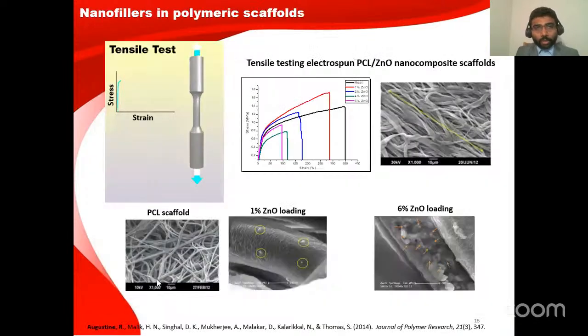We used nanofillers. Nanofillers are nanomaterials that are incorporated in the polymers to improve the properties, especially the tensile properties. We found that when we incorporated zinc oxide nanoparticles in the electrospun scaffolds, there was an improvement in mechanical properties at optimal concentration. The importance of such research is that we need to find the specific concentration of the nanomaterials used in the scaffold. For example, here 1% of nanomaterial seems optimal, with enough mechanical property, while when we incorporate 6% zinc oxide nanoparticle, because of the agglomeration that you can see here, the properties decreased.